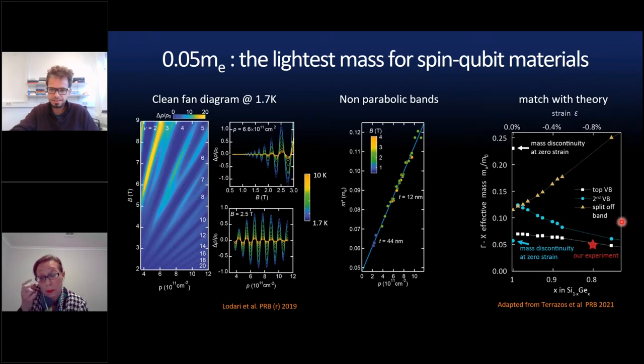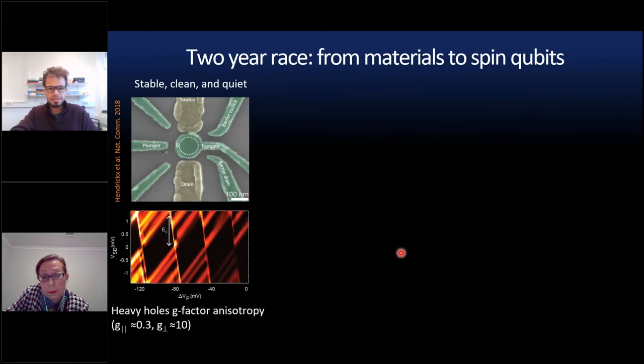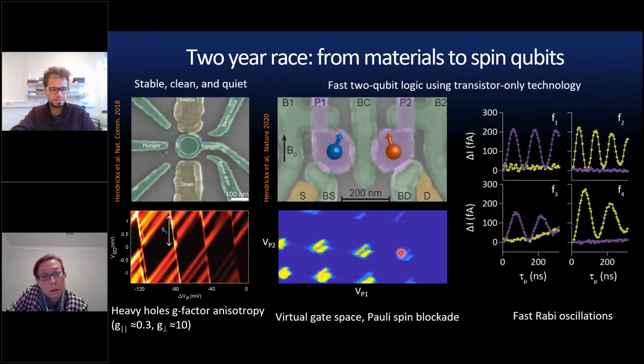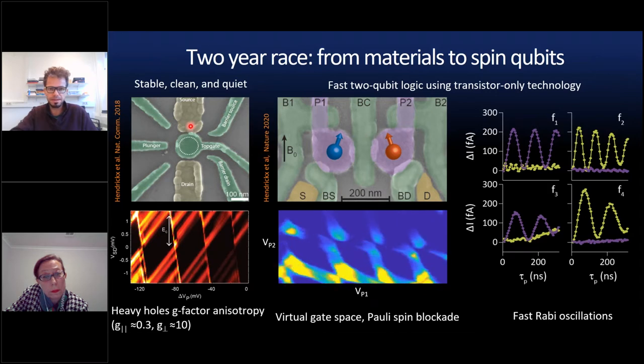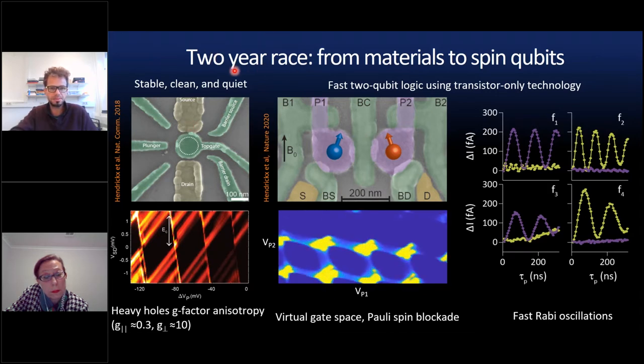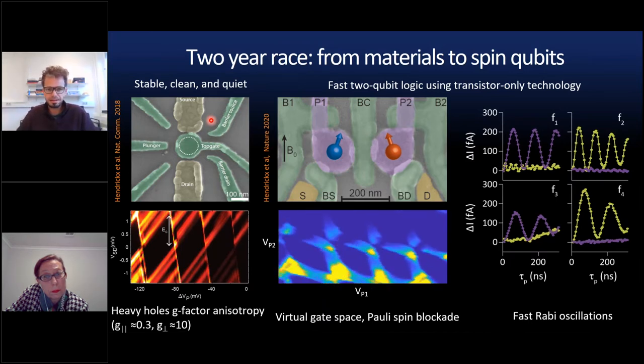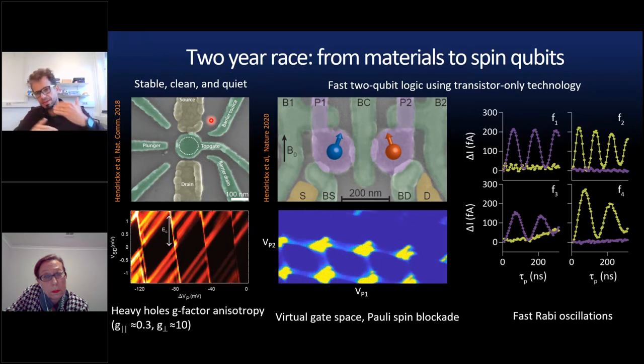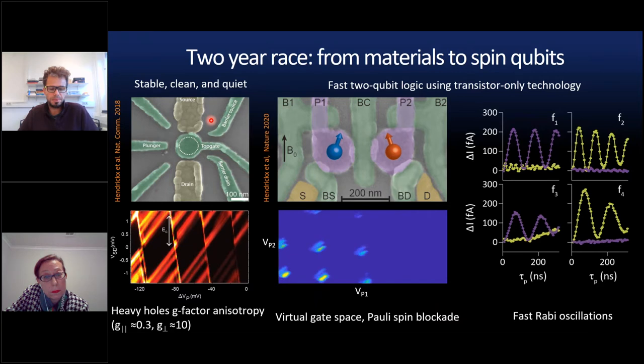And again, the nice thing is that you can do all the theory and the experiments match with the theory, which is very neat because it means that you can really design your structures and make them in the lab and then implement feedback loops to go back and tune your parameters. So with this material now in place in 2018, after a couple of years of working on this, we were able to go, in only 2 years, from materials to spin qubits. It took silicon many more years and gallium arsenide even more to get to this point. And of course, all the know-how we had helped, but also these intrinsic properties of the material are the origin of this really fast progress.